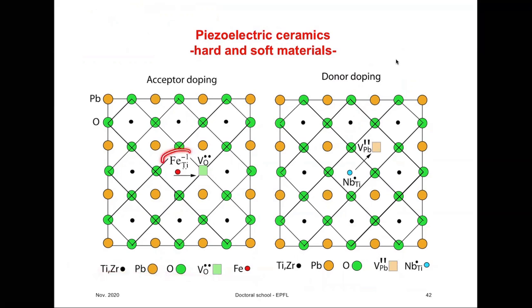Here is iron on titanium side, which is negative. Here is niobium on titanium side, which is positive. We assume that iron is surrounded by oxygen vacancies, and that niobium is surrounded by somehow lead vacancies.